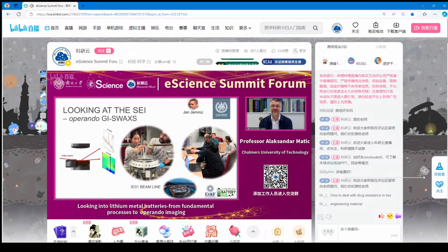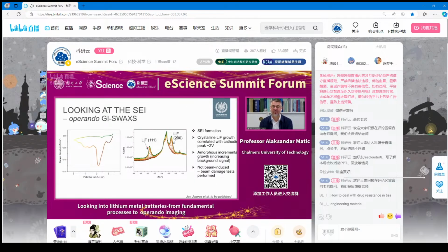So here is one of the results. Also, this is work in progress, which we hope to report to you in detail during the coming months. But what we do here is that we do a CV, a potential sweep, where in the electrochemical cell, we are now looking at a copper surface, single crystal copper surface, and we are doing the CV, so we are breaking down the electrolyte, and as we're doing this, we are recording diffraction patterns in this case, and as the electrochemical process goes on, you can see here how we continuously, for instance, start to form lithium fluoride.